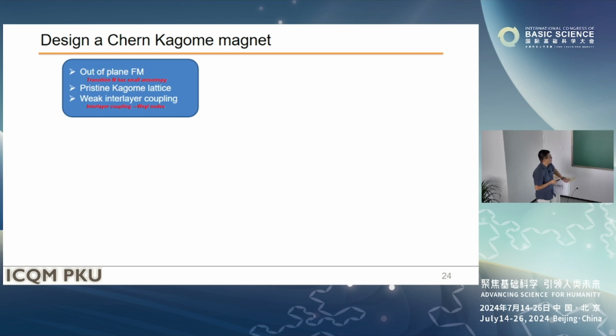This is just a rough idea in mind. So what should we look for? We expect to find a magnet which has out-of-plane ferromagnetism, right? This is the model suggested. And we have a pristine Kagome lattice, undisturbed. And the interlayer coupling, we prefer to be very weak, because if you have strong coupling, that becomes three-dimensional physics instead of two-dimensional. So unfortunately, if we look around at Kagome materials formed by transition metals, we find that basically they are more like 3D, and also because transition metals have small anisotropy, you don't find out-of-plane ferromagnets. Usually the magnetism is in-plane or antiferromagnetic.